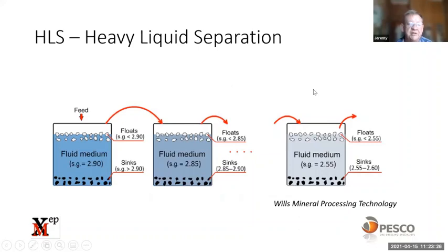Heavy liquid separation, that's basically you make up a fluid medium of different densities. You add the feed. In this example, your medium is 2.9, so you'll have a floats at 2.9, and the stuff that's heavier than 2.9 will sink. The floats, then you transfer to the next one, which is 2.85. So then you'll get the float, so the stuff that's lighter than 2.9 but heavier than 2.85 will sink, and then you'll get the sinks. And so you continue the process.